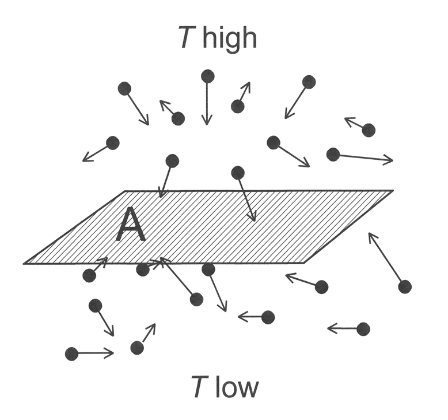Mid and long wavelength phonons carry a significant fraction of heat, so to further reduce lattice thermal conductivity, one has to introduce structures to scatter these phonons. This is achieved by introducing interface scattering mechanisms, which require structures whose characteristic length is longer than that of an impurity atom. Some possible ways to realize these interfaces are nanocomposites and embedded nanoparticle structures.